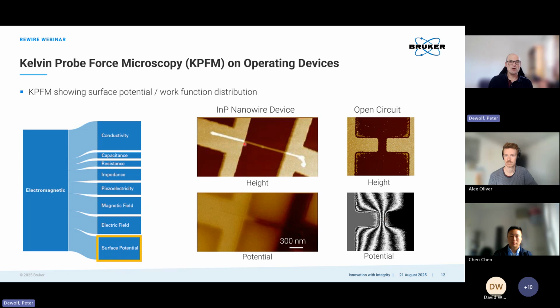On the nanowire as well, we can see how the potential varies from one contact to the other as we're applying a voltage between the two contacts. But also along the nanowire, we can see, for example, here there's a little bit of a jump in the potential profile that indicates there's actually a defect in that wire that was not expected.